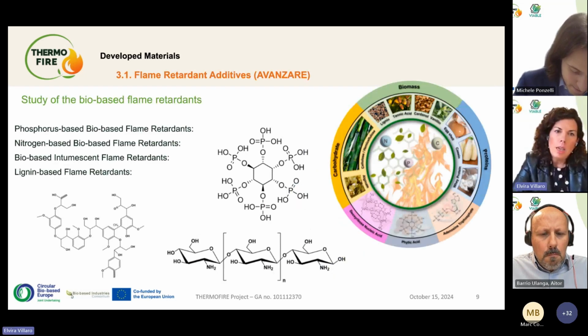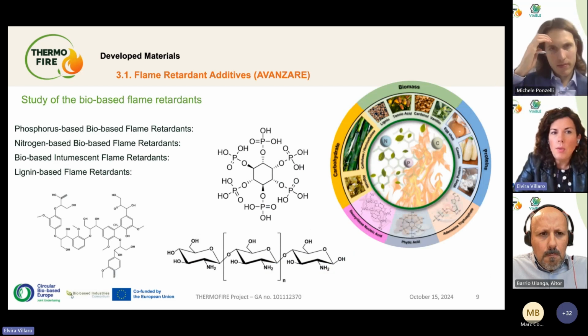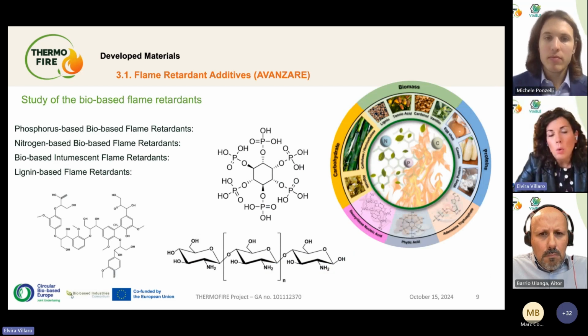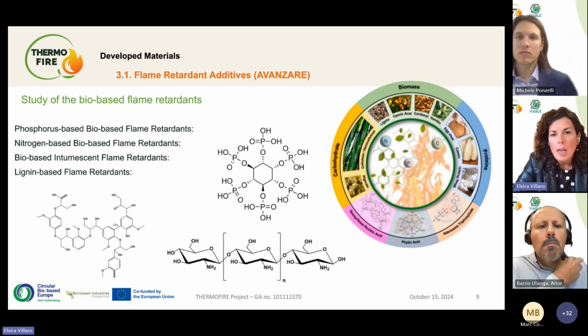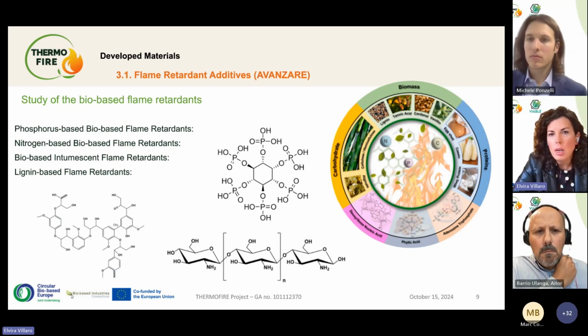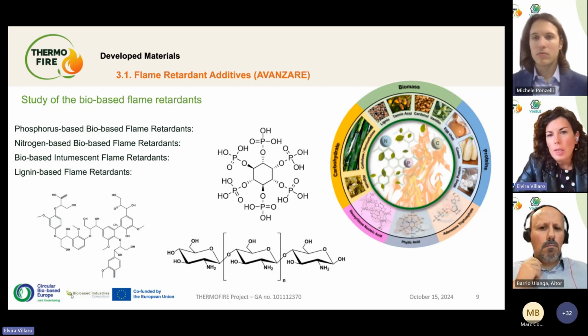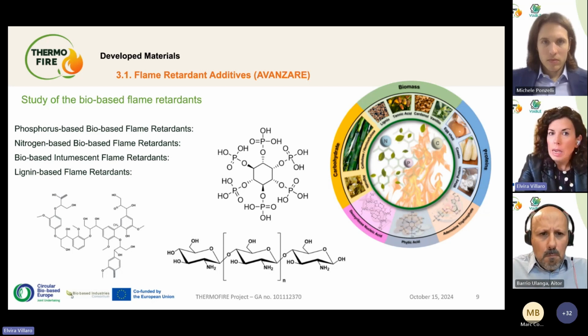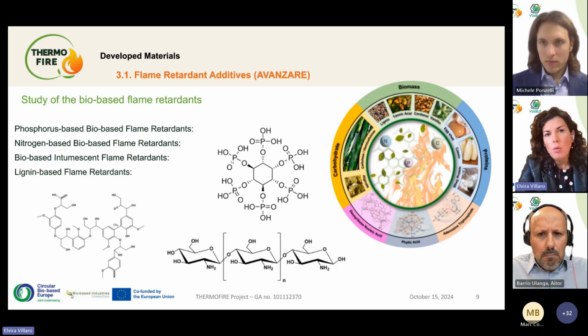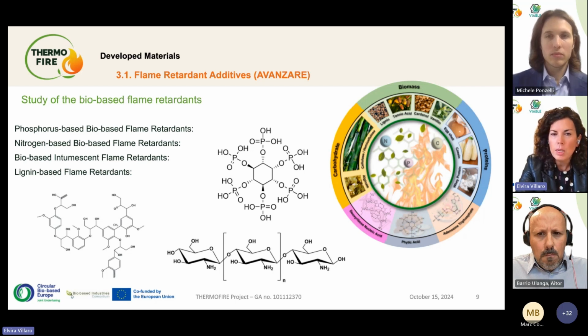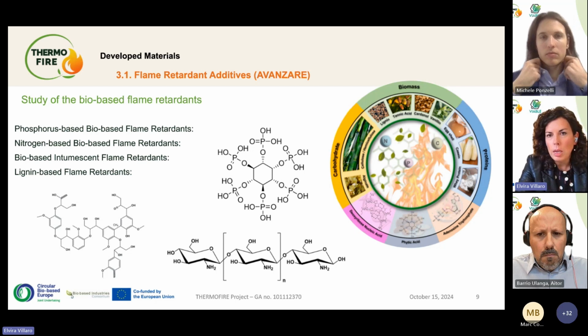So if we start with the flame retardant additives, we are using different bio-based additives containing nitrogen and phosphorus. For example, we are using some derived from lignin, which Mark has explained perfectly in the process. And we are also using chitosan. You can see the sources from which we are obtaining the phytic acid, the tannins, or other materials that we are using as flame retardants. As we are going to explain now, we are not using only one material for the flame retardant performance. We are using several of them to achieve a synergistic effect and a good performance against the flame.